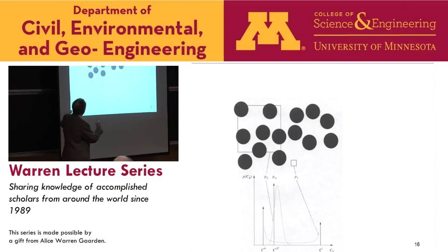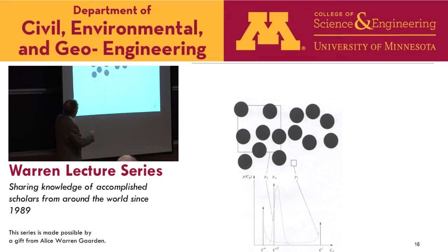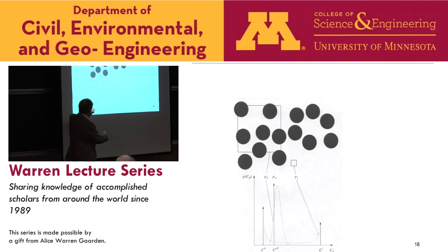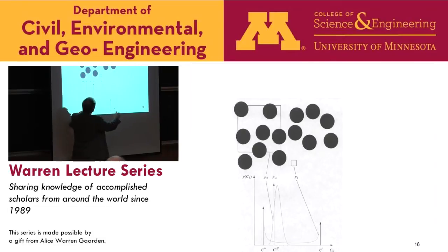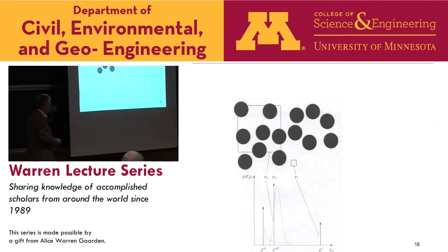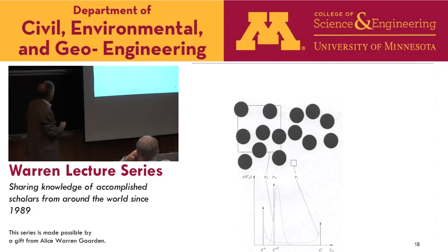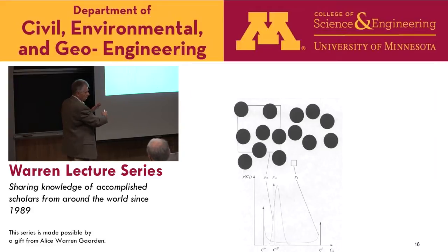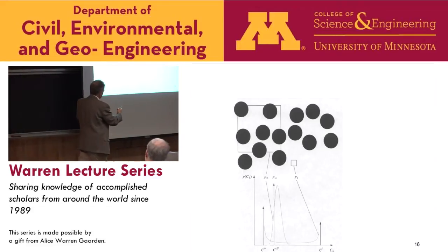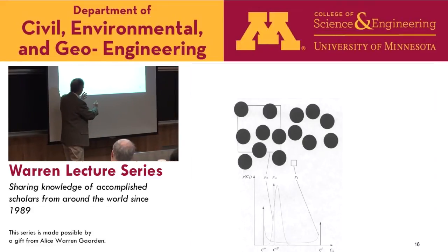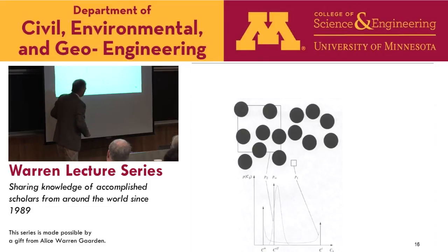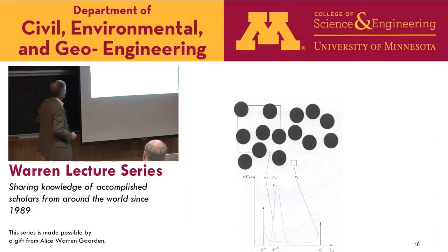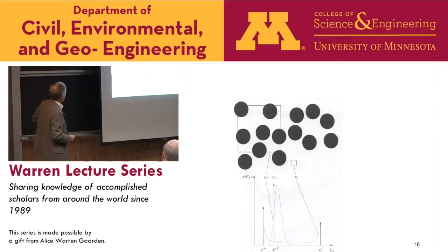If I sample by a window which is even bigger, then I will always have some inclusions inside, and the probability density becomes kind of bell-shaped, but not Gaussian. It's bell-shaped between these two. So a natural model for this from statistics is a beta probability density, which represents this flow of probability distribution, or probability density, as I change the scale. So there are various results like that.